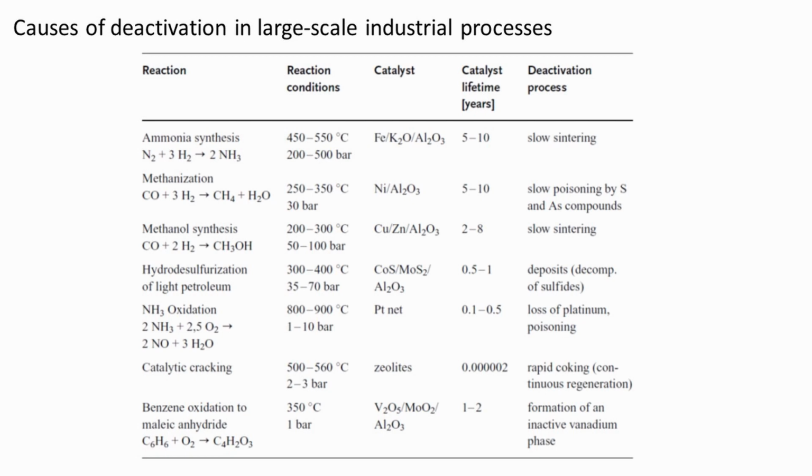Its surface, pores, and voids may be fouled by carbon or coke produced by cracking reactions of hydrocarbon reactants, intermediates, and/or products. In the treatment of power plant flue gas, the catalyst can be dusted or eroded by and/or plugged with fly ash.